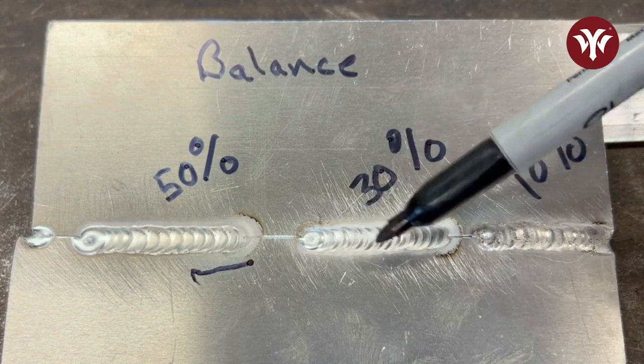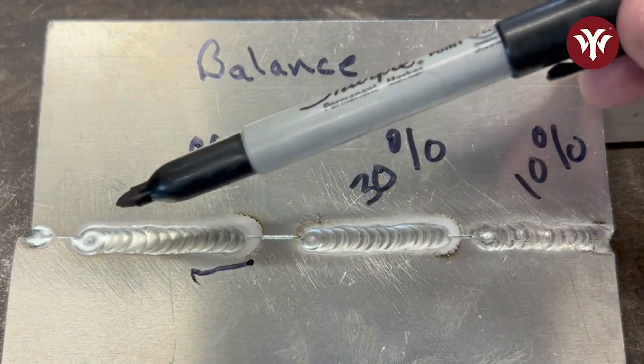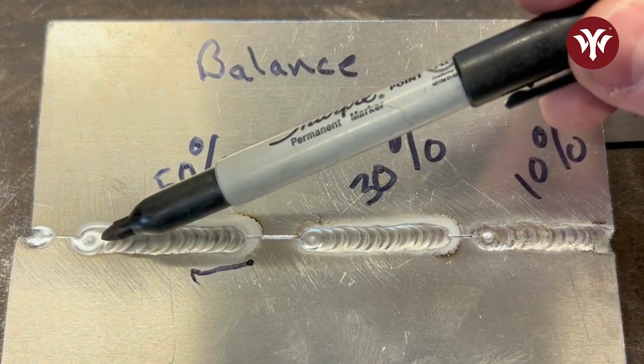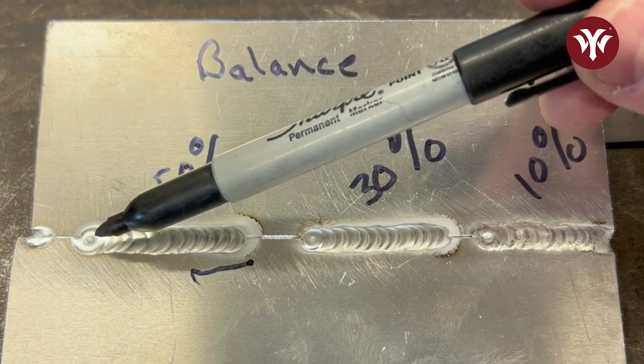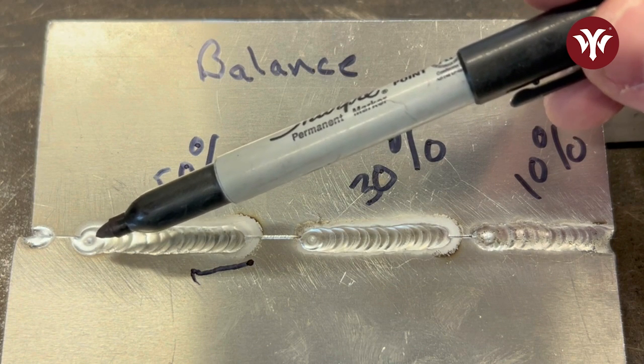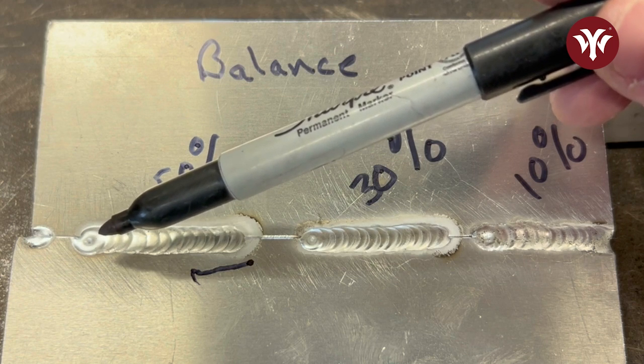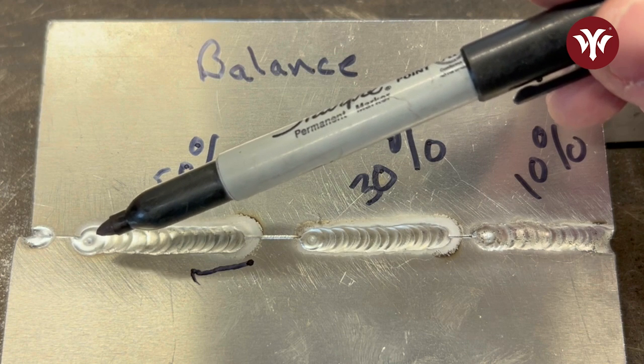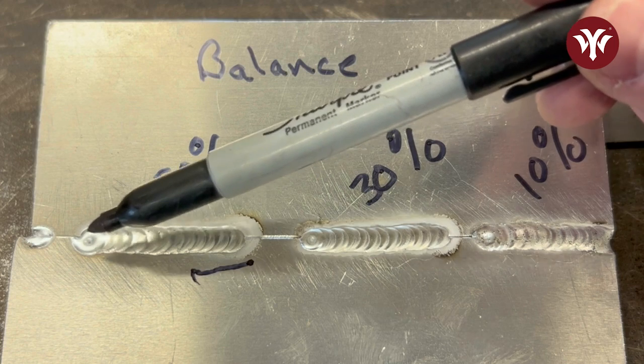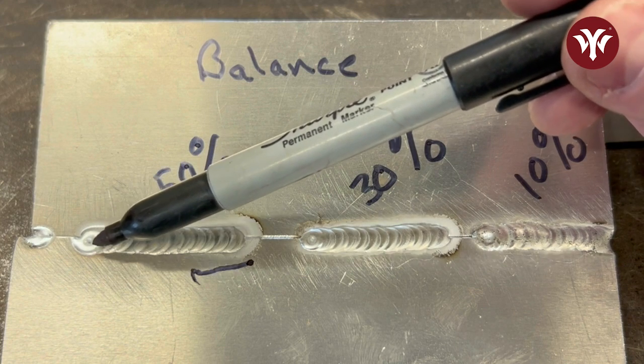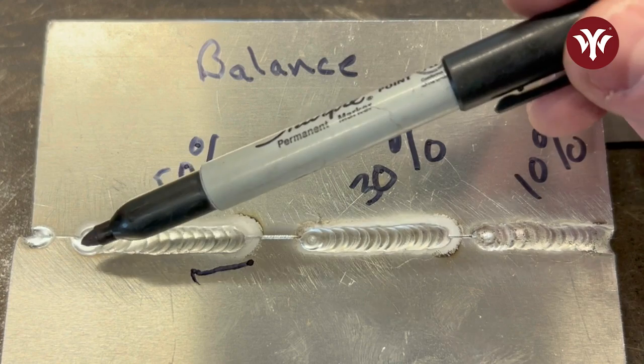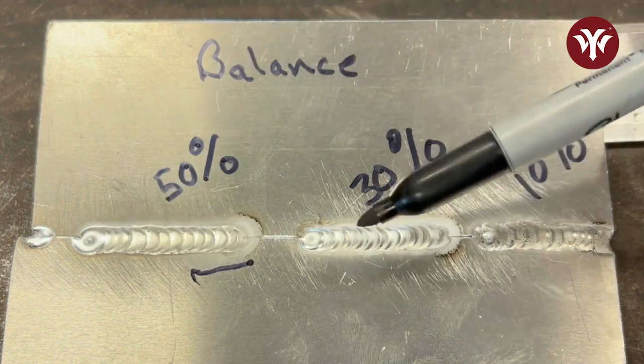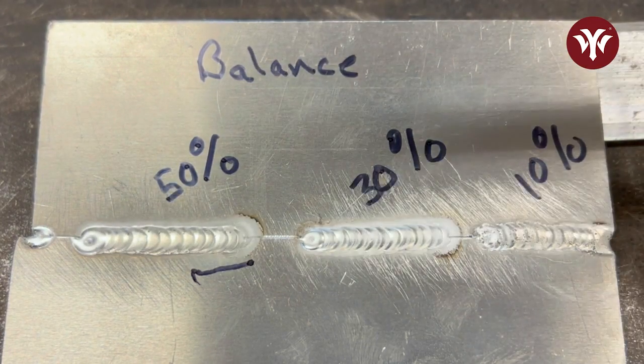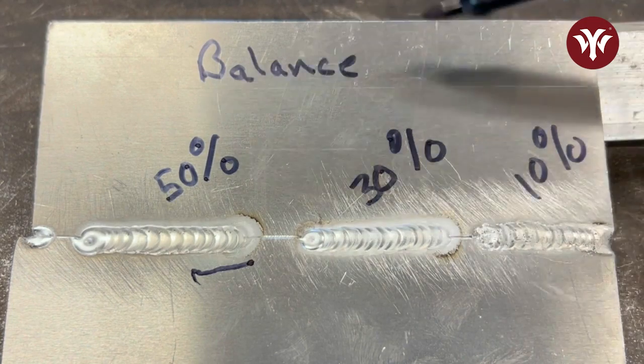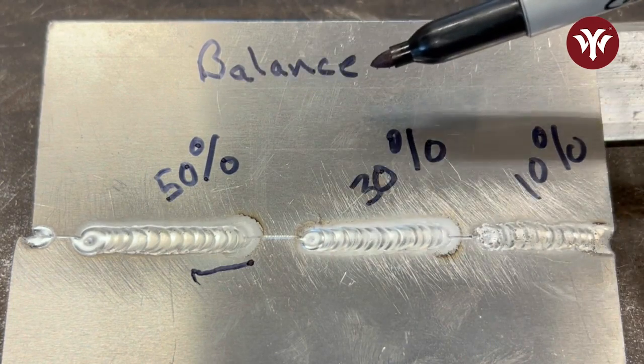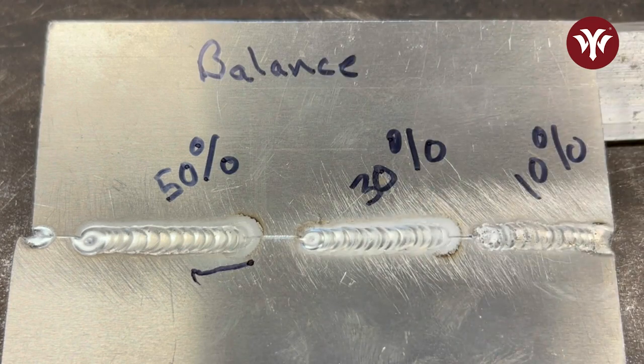But effectively, between weld to weld, there isn't a lot of difference. I didn't really crater fill this, so you can see that little hole there is the crater we're talking about when you finish a weld. The best way to fill that is to slowly ramp down the current with your foot pedal while giving it just a little bit of an extra dab of filler rod at the end. Let the puddle fill in, because that little crater there can very easily lead to a crack migrating down the weld. And here I did crater fill it. So there's a little bit of a difference. I hope that explains what balance is and the effect of adjusting that balance.